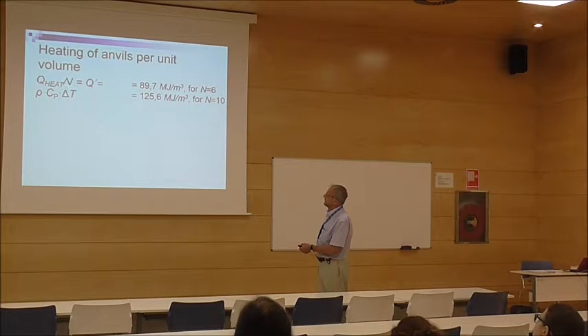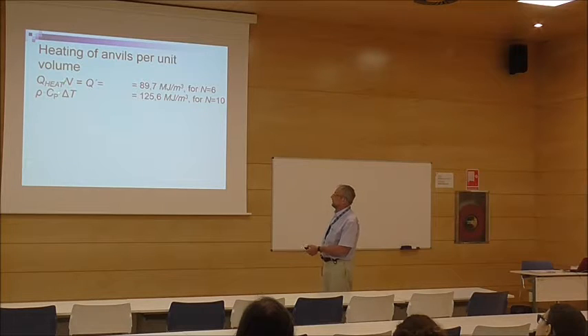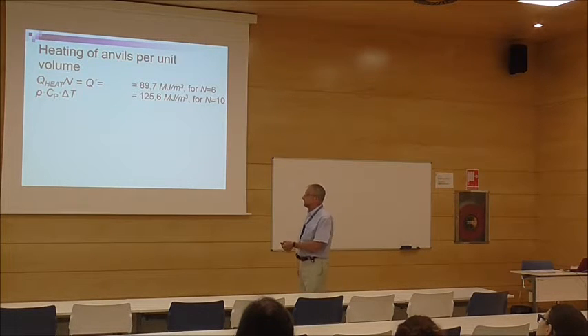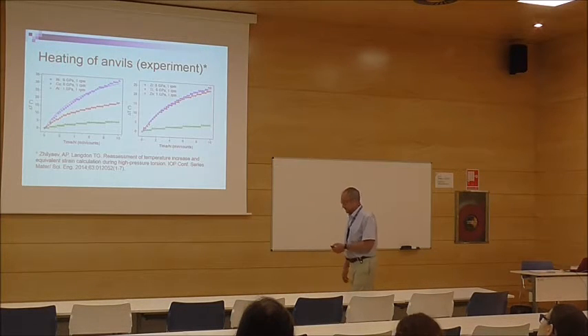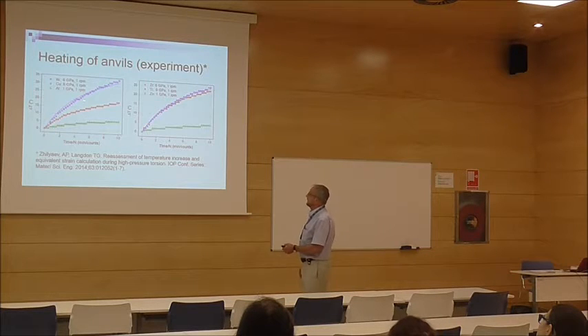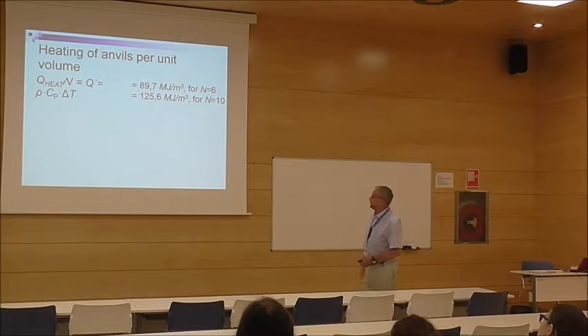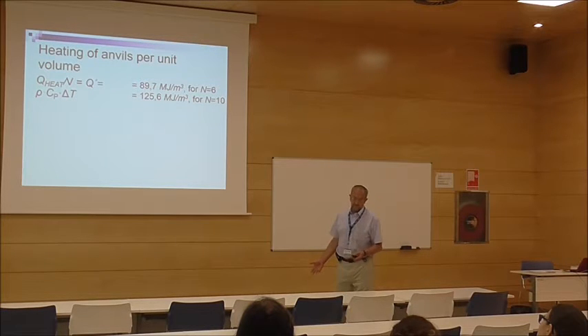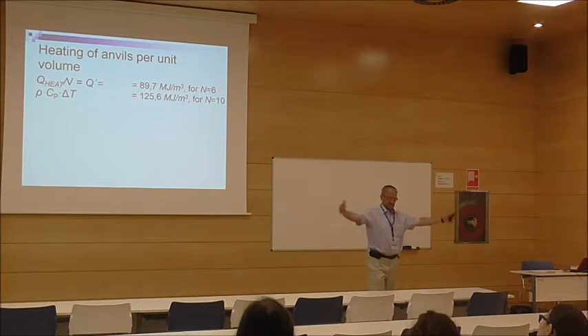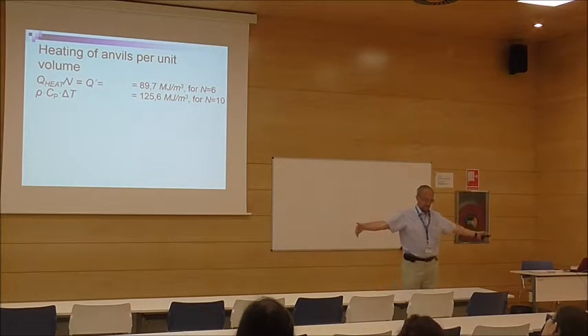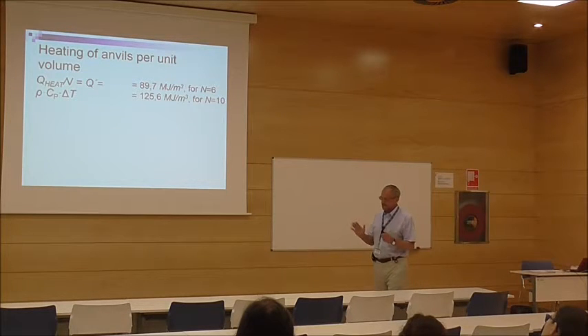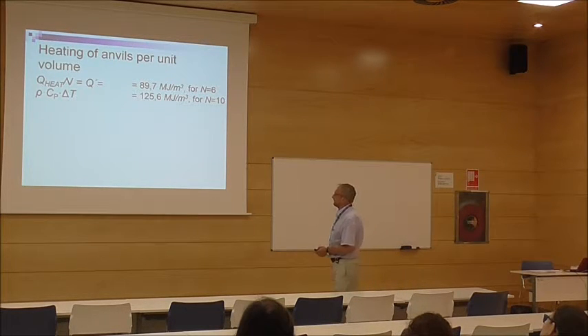This is per unit volume. This is just density, specific heat capacity, and the temperature difference. You see the different temperature for 6, like 25 degrees, for 10 it's 35 degrees. So just a very simple calculation gives you quite a big amount, 90 megajoule per cubic meter. It's a huge amount, but remember, a cubic meter is huge, and this is just for unit volume.